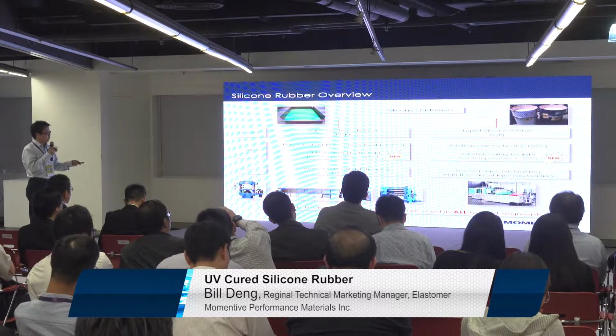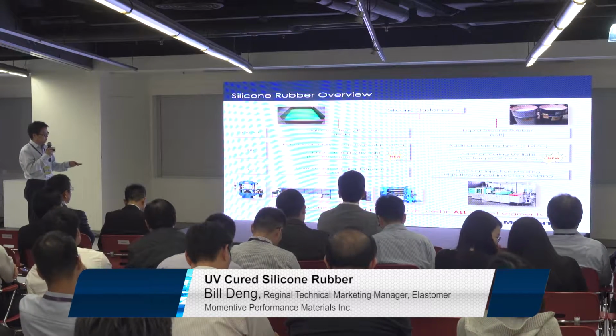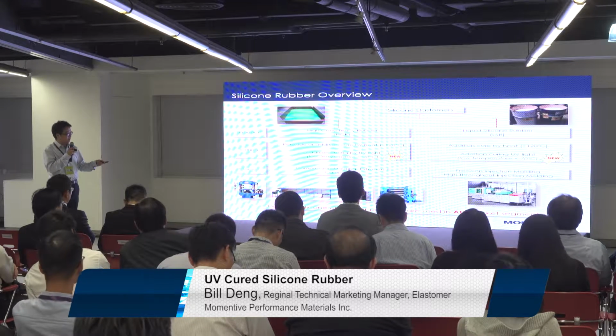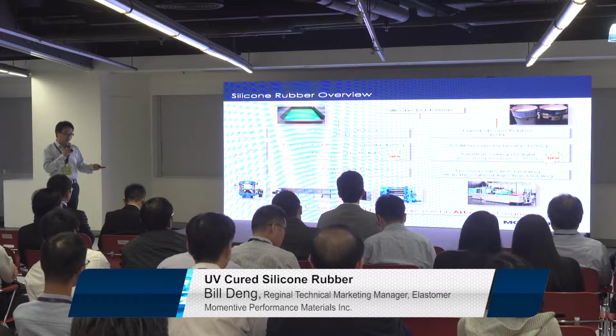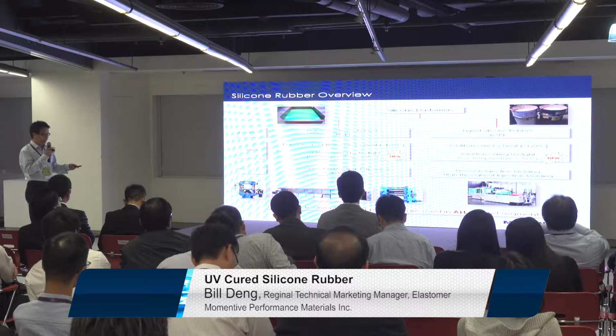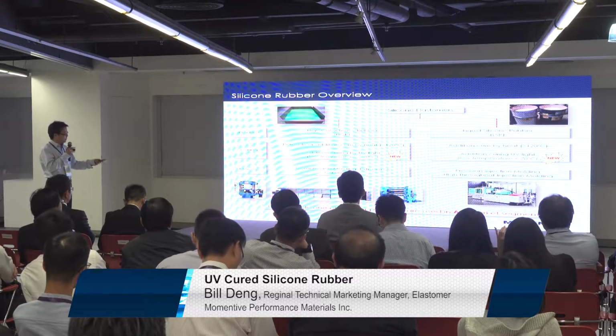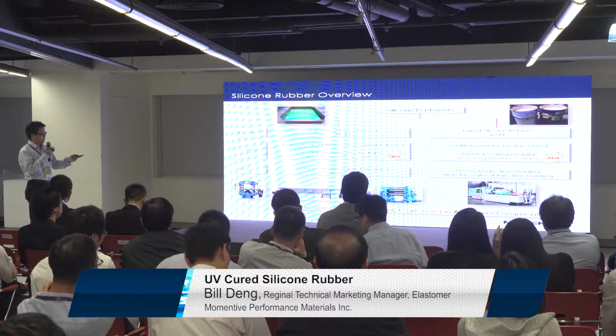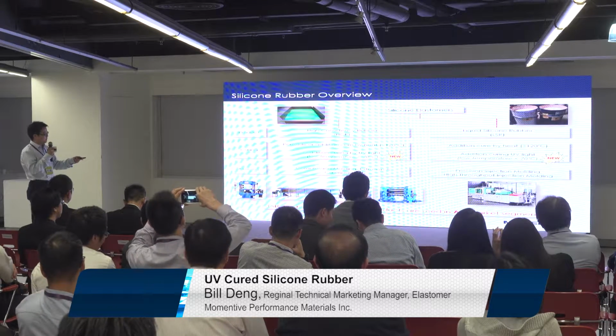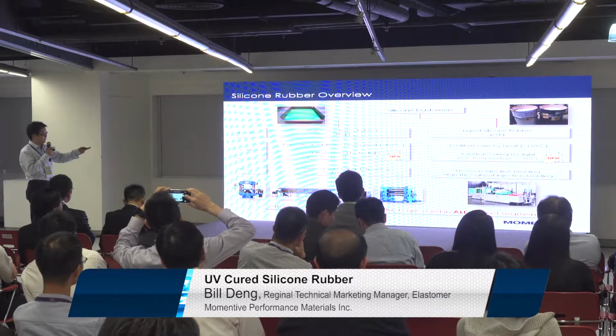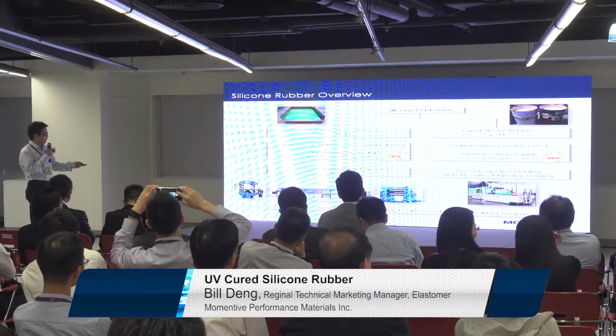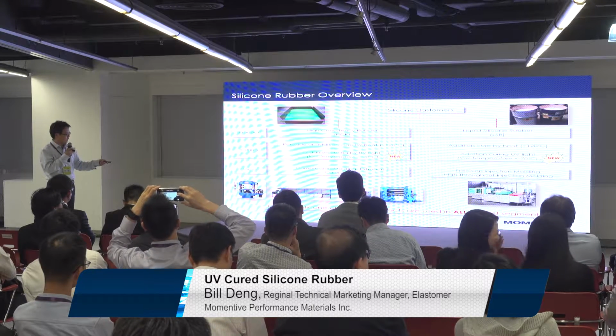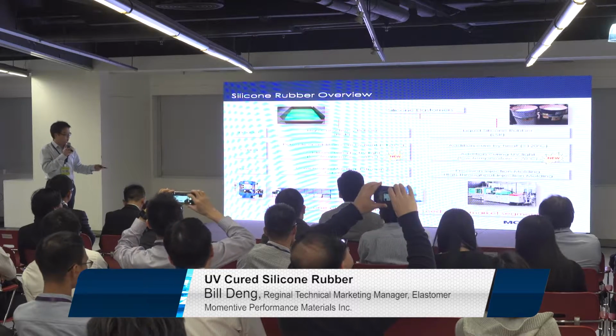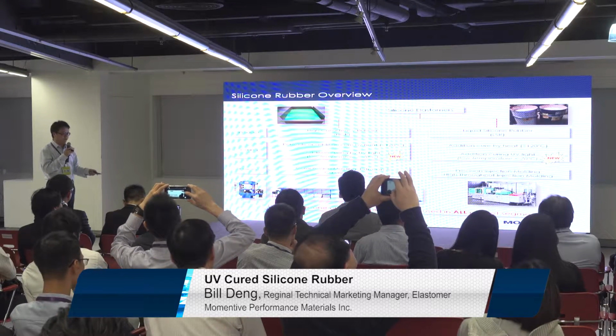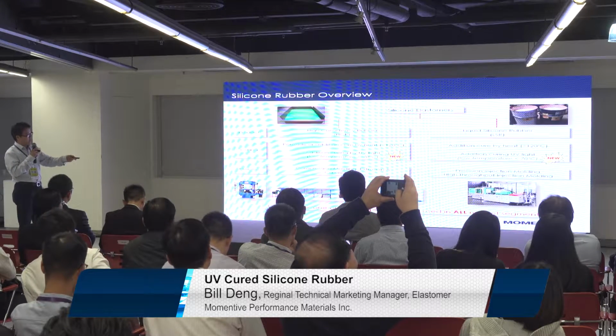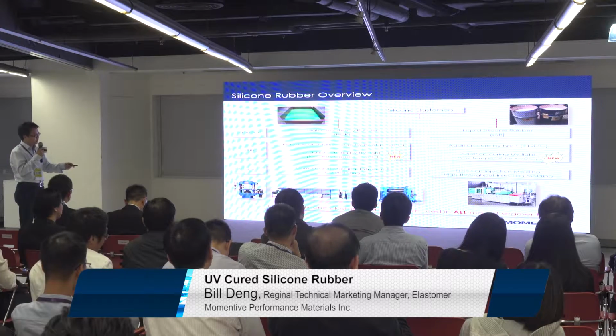In that way, we can cure the material at less than 70 degrees, and UV cured LSR can also be injected into the injection molding machine at less than 70 degrees. And this applies to both UV cured material and regular elastomer material. In the processing facility, usually for HCR, we have compression molding machines and also extrusion machines for tubing, like medical tube, and calendaring for silicone rubber film. But for LSR, there is always a high precision injection molding machine.